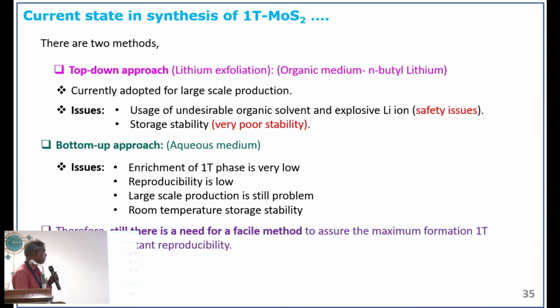So it's not possible. So the bottom-up approaches are there, in aqueous based medium. But the enrichment of the 1T phase is very minimal. Even though we can use this aqueous medium, only 10% or 20% will be grown. We cannot grow beyond this. And then reproducibility is very low. A very important thing is that whatever ionic components you place inside affect the growth of the 1T MoS2.